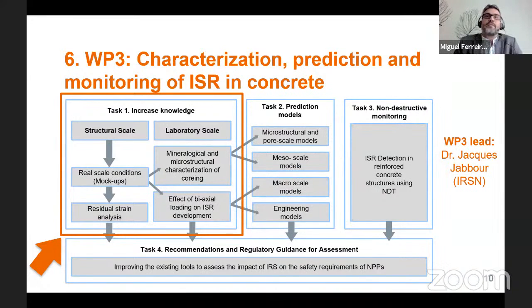Task 2 addresses modeling and the prediction of long-term expansion of structures affected by ASR in power plants. The objective of this task is to develop a series of numerical models that simulate the occurrence and the evolution of the swelling, of the expansion in the concrete. And this includes spatial propagation, the mineralogical alterations that can occur, crack formation and intensity as well. The intention is that the modeling activities will be conducted on several different scales, starting from microstructural and pore scale, and this will provide process understanding, and this continues into mesoscale and macroscale to make prediction on the scale of the real structure.